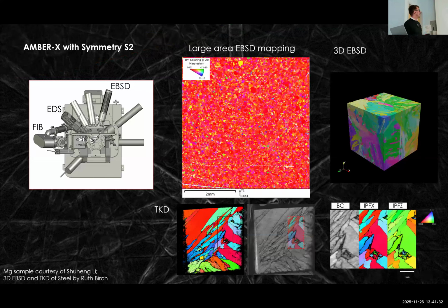So this is the Amber X. We've removed the electron column for convenience, but the EBSD is pointing off to the side. You're looking down the top. It has EDS and a few other devices. This is a large area magnesium map. To do that indentation, it's like finding a needle in a haystack for the grain you'd like to indent. So we do the EBSD, we pick this grain, and then we go and zoom to it in the nanoindenter, poke it, and then we take it out, and we then do lots of work afterwards.